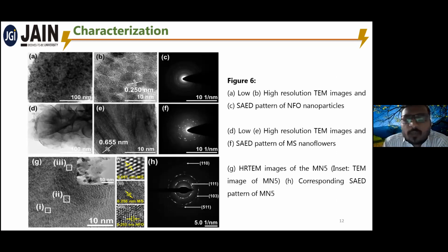These are the TEM images of our bare nickel ferrite, MoS2 nanoflowers, and our catalyst, MoS2 nanoflower with 5 mg addition. The interlayer spacings are well matching with the planes of the respective materials. From the SAED patterns of the nickel ferrite and MoS2, we can observe a semi-crystalline nature, while from the nanocomposite SAED we can say that a polycrystalline nature is present in the nanocomposites.